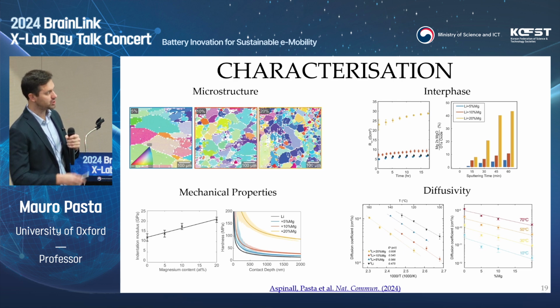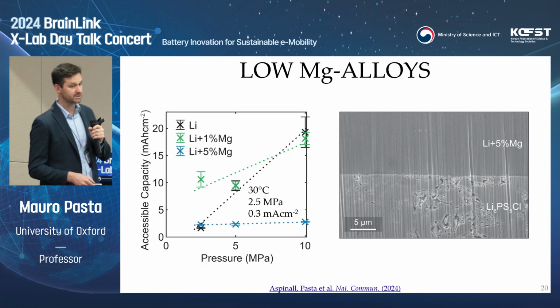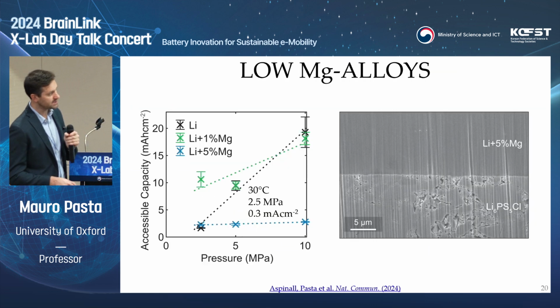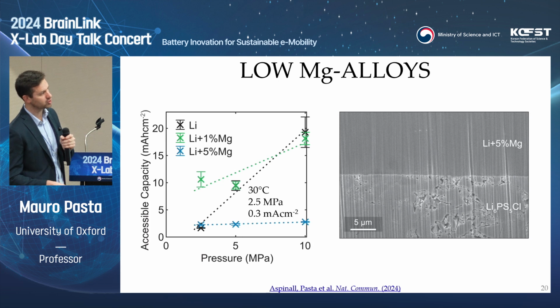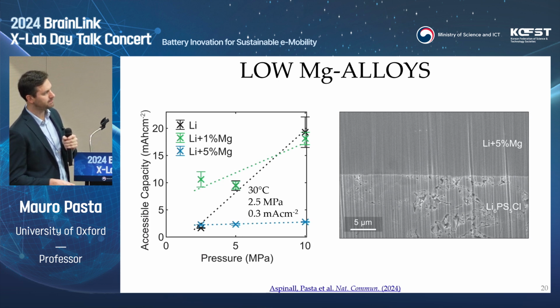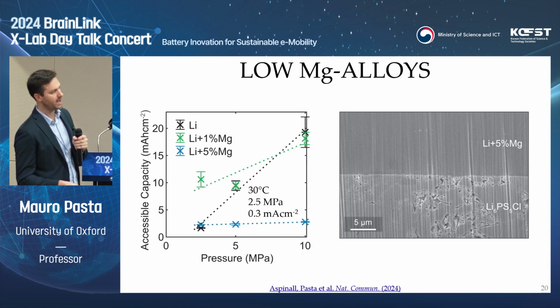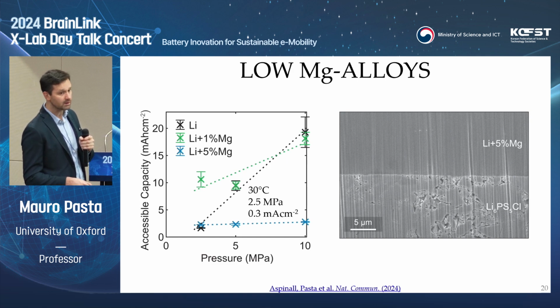Now, a couple of takeaway messages for this specific system. As you're adding more magnesium, your alloy becomes harder and the diffusivity is decreasing, which is exactly what you do not want from a transport point of view, but it's quite beneficial and helpful in terms of contact retention. So if you look on the right-hand side over here, you have lithium magnesium on top and your solid electrolyte, not particularly densified in this case. We'll talk about that in a second. As you strip the lithium away, the magnesium is left, and therefore it allows you to retain contact without the generation of the voids that I mentioned earlier.